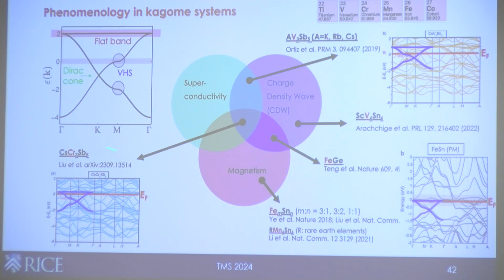So if you keep going, this is maybe one of the more recent members. This is a chromium-based 135. It's isostructural to the vanadium 135. And in this system, the chromium is in between vanadium and manganese. You can see the flat band is also in between these 2 cases. The flat band is closer, but not yet quite at the Fermi level. And this is also a very interesting system that's starting to give us phase diagrams that look like the cuprates and so on and so forth. Anyway, I'm going to talk about this at the very last end of this.